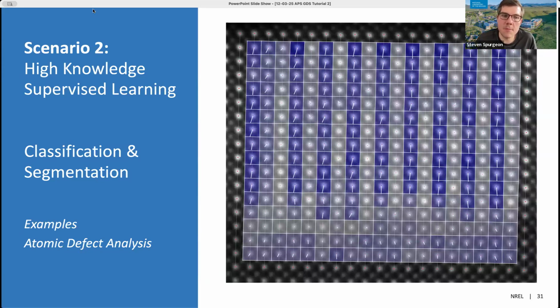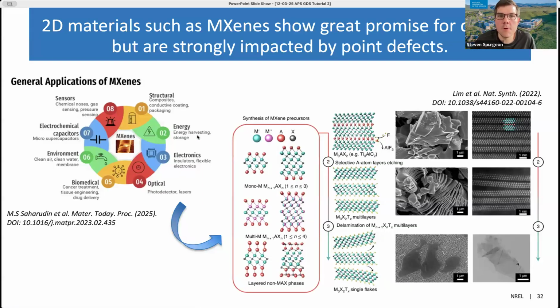And so here we're going to take the same problem of atomic defect analysis, but we're going to try to address some of the challenges that were laid out in the previous example. So much of the work that we're doing recently has been focused on 2D materials. We're focused on materials like MXenes that are one of many classes of 2D materials with promising properties for a range of applications. In particular, MXenes are transition metal carbides or nitrides, tend to be one or several layers of these materials that are exfoliated from a bulk crystal. And they have very interesting properties for electrochemistry, for separations, for optical applications, sensing, all kinds of different needs.